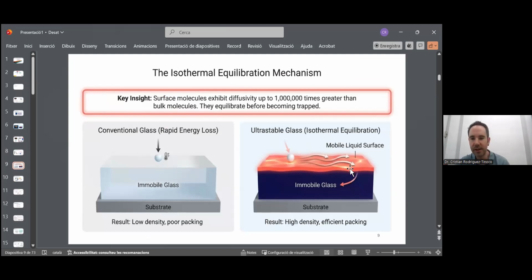Okay, there is a temperature range in which we can optimize this surface mobility and get a more stable glass. And this is what we get when we grow the system at 85% of the glass transition temperature. If we grow this thin layer by physical vapor deposition, which is the glass, at 85% of the glass transition temperature, we will get a glass which has very large stability.